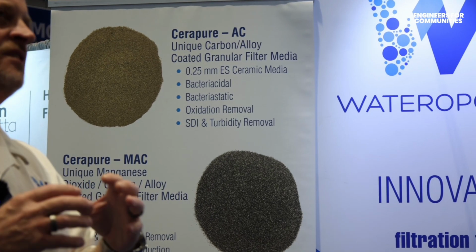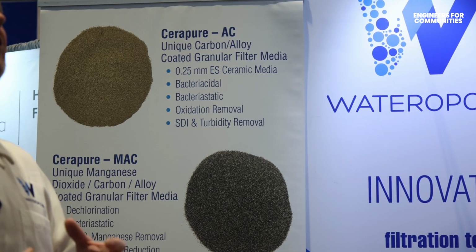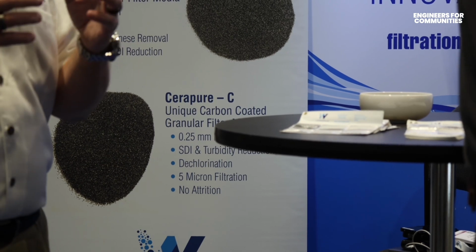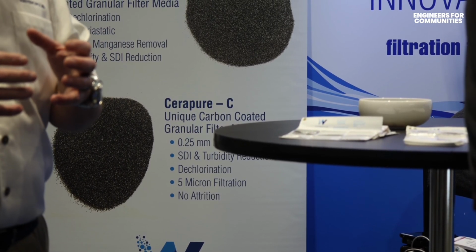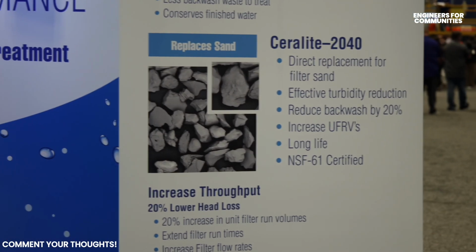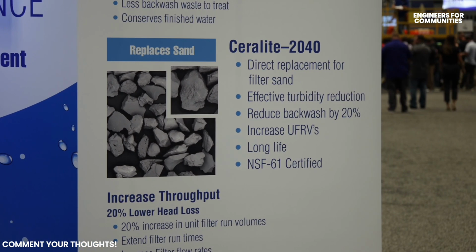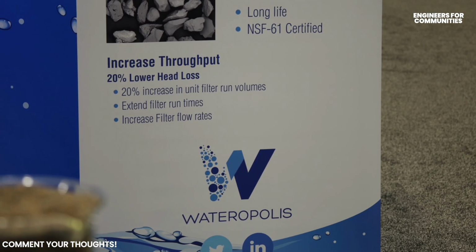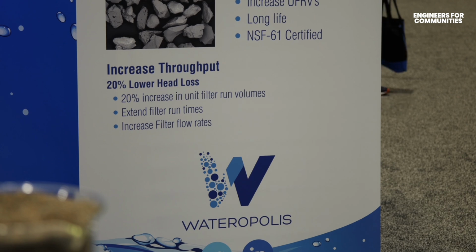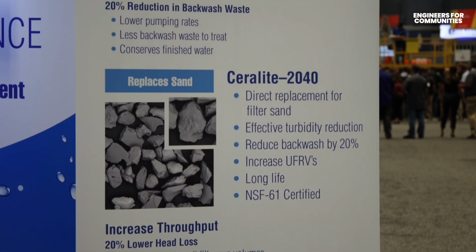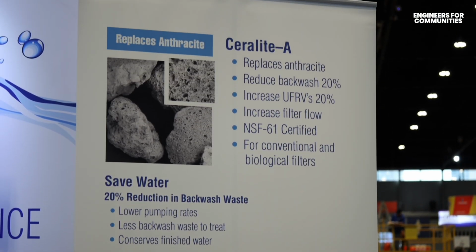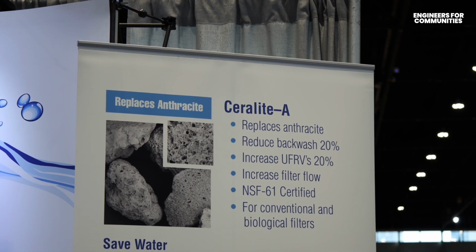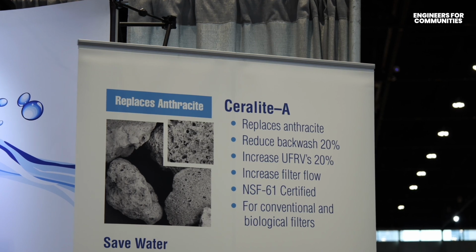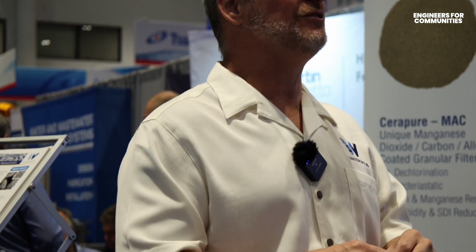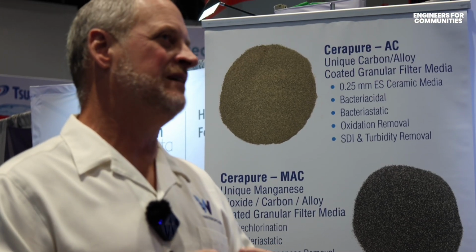And when you get a high dissolved oxygen content in your water, you can actually start to get biological growth in your filter. And biological growth can, if it's done wrong, actually stunt the removal. So we actually add an antimicrobial component through a copper zinc alloy to our media to prevent biological overgrowth, because manganese removal requires a catalytic surface. And if that catalytic surface becomes covered in biomass, it's not catalytic anymore. The water's not actually touching it. So in those situations, we have intentionally tried to deter biological growth if we have a chemical that's reverting back to oxygen. We have other applications where we actually want to grow biology, where you can do biological iron and manganese removal. In that situation, you intentionally grow microbes, and those microbes digest iron and manganese as part of their metabolic process. So that's another way to do it. Different way to tackle it.